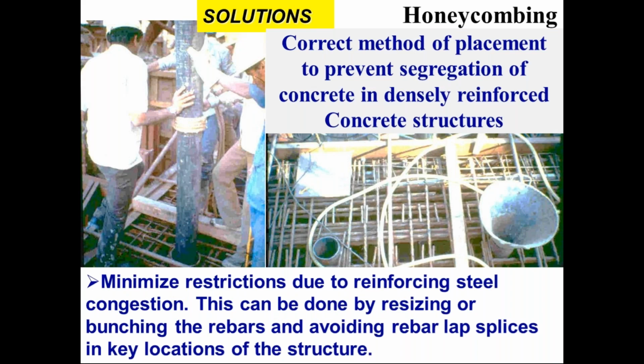First of all, you must space the bars properly so that the concrete goes into the lower layers of the structural member without segregation. Minimizing the restriction due to reinforcement steel congestion can be done by resizing the bars. You can use larger diameter bars, and also you can bunch the bars together. It is allowed as per the standard IS 456, and as far as possible you should not have lapping done at one point, because laps will again create congestion.